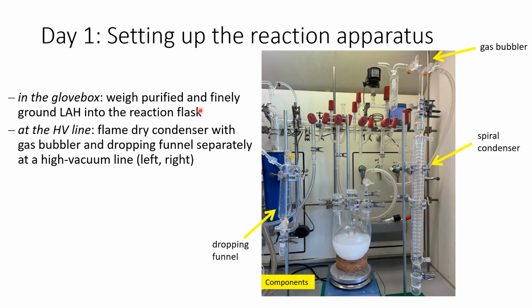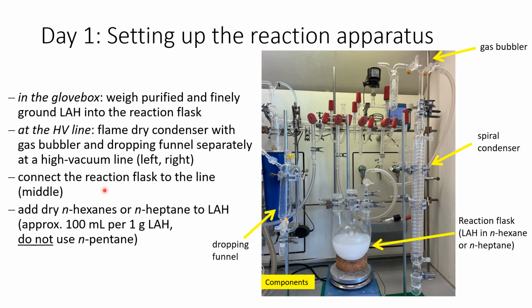Then, during the same time, we attach our other glassware to our high vacuum line. So we attach the condenser with our gas bubbler, as well as the dropping funnel, separately to the high vacuum line and additionally heat them with a heat gun under vacuum. Then we take the reaction flask and also connect it to the vacuum line. This is shown in the middle here.